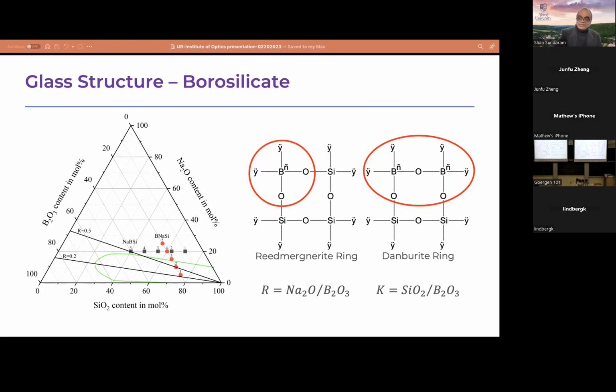So we use ratios like R and K. R is the ratio of sodium oxide to boric oxide. K is the ratio of silica to boric oxide. We use these to describe our glass structure. You can see boron can be connected to oxygen as part of the boron ring. This is what we call a Reedmergnerite ring, a structure we find in glasses. And we also sometimes see boron connected to oxygen in the network. We call that a Danburite ring.